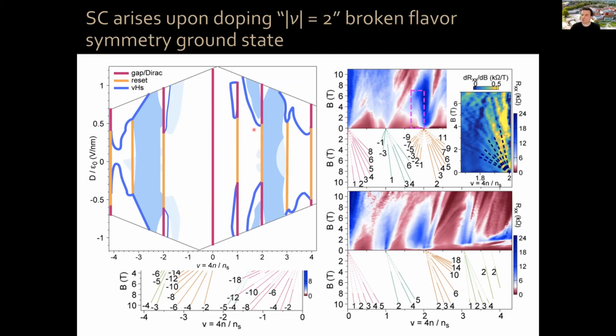So you go to a nu equals 2 symmetry broken phase with 2 Fermi surfaces, but because you do it before nu equals 2, these 2 Fermi surfaces are hole doped. And that's why you have this branch, okay? The superconductive branch corresponds to hole doping of the nu equals 2 many-body ground state. This part corresponds to electron doping of the nu equals 2 many-body ground state.